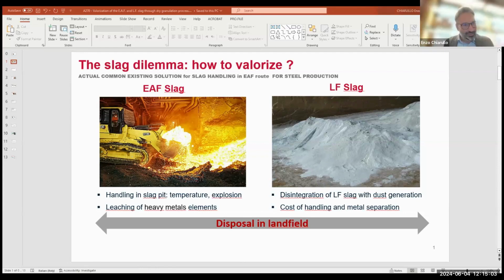It is for this reason that Tenova, since 2016-2017, developed the technology based on forced air slag granulation, with a European patent, which permitted the ultra-fast cooling of the liquid slag, both ladle furnace and electric arc furnace slag, through the blowing of forced air, in such a way that we can obtain mineral fraction and metal fraction of this slag in solid form and in dusty phase. The rapid solidification will permit to obtain a glassy amorphous material, which will be of more interest for the construction industry as a new possible raw material for the slag.